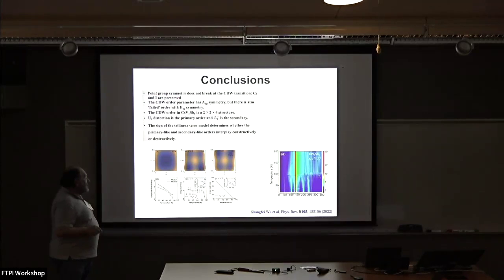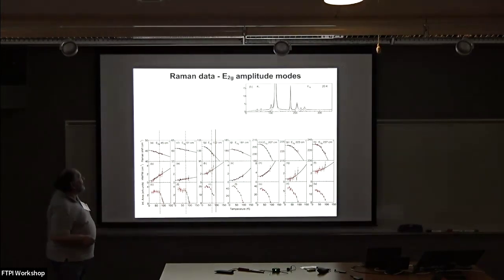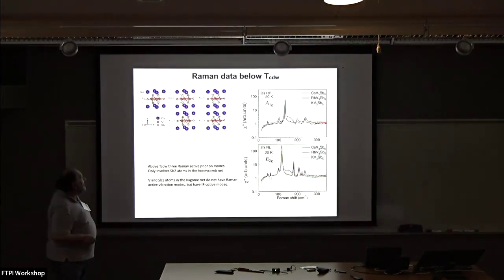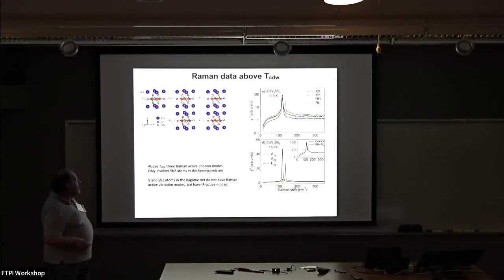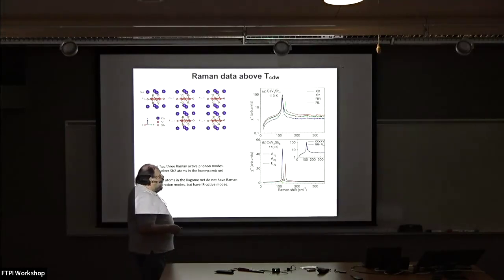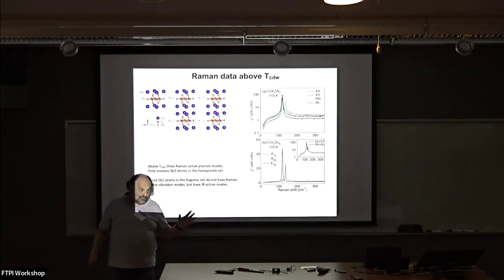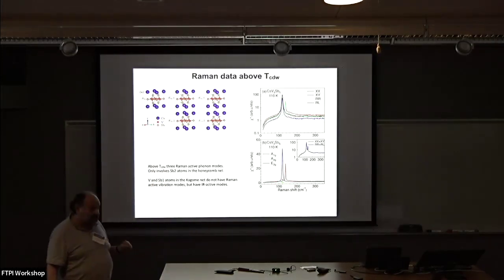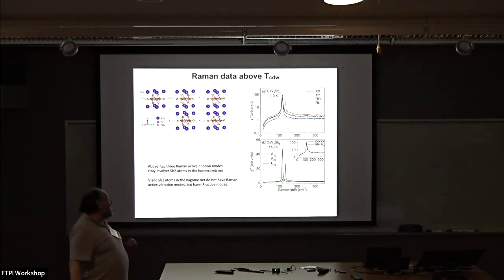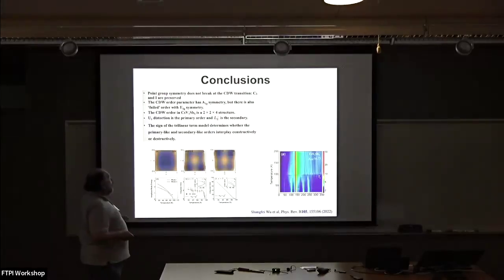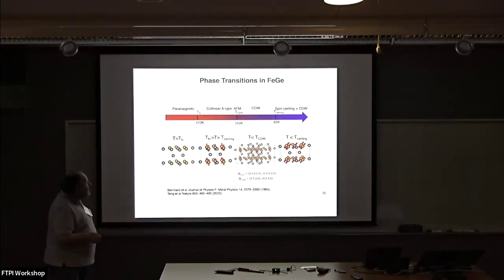Now, it's difficult to see any reason for broken time reversal also from the perspective of this plot, because when we look for the instability, we do the symmetry analysis of all modes, and we see nothing in this so-called antisymmetric XY exchange, A2G representation. And the A2G representation is the only one that is compatible with broken time reversal. So we don't have anything to grapple with. I'm quite skeptical that all the claims of broken time reversal symmetry are relevant.